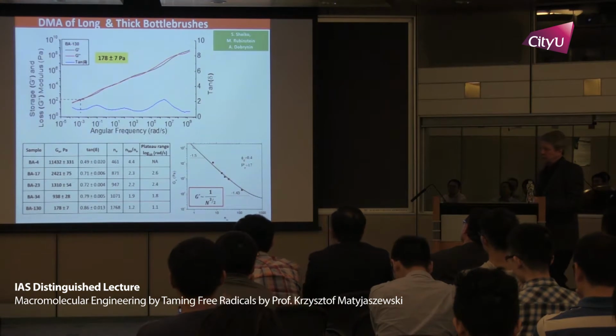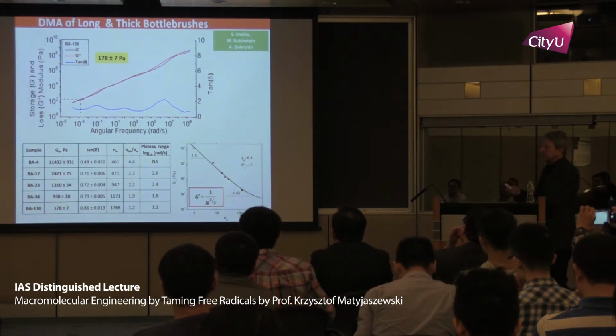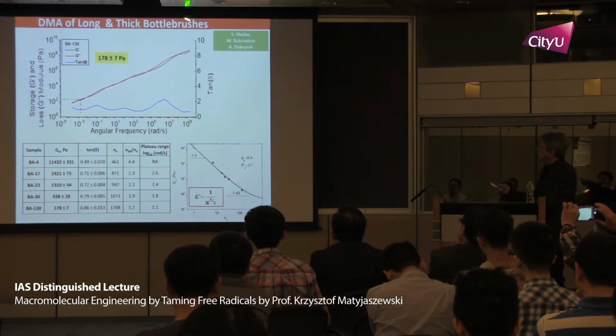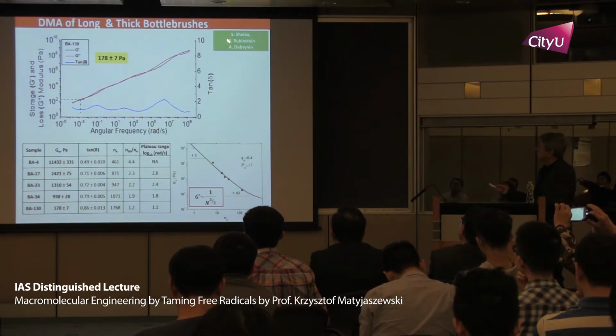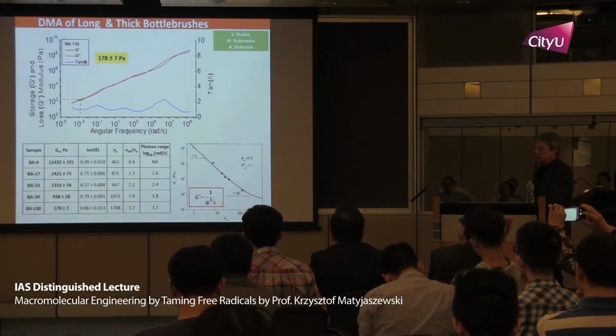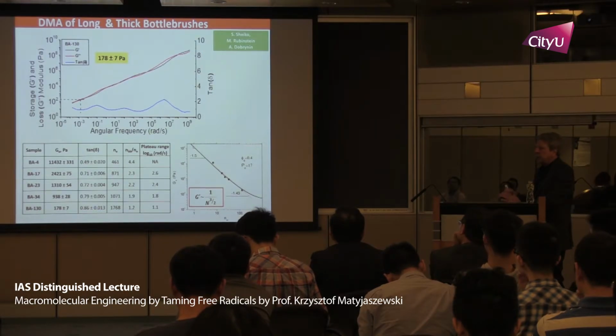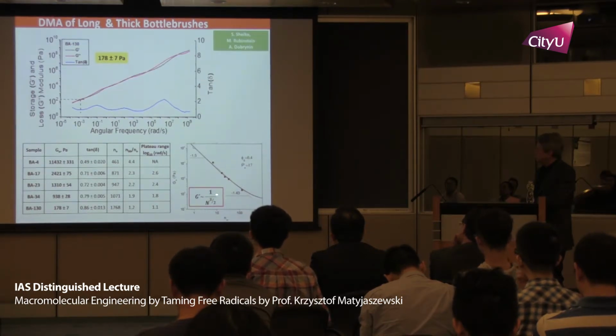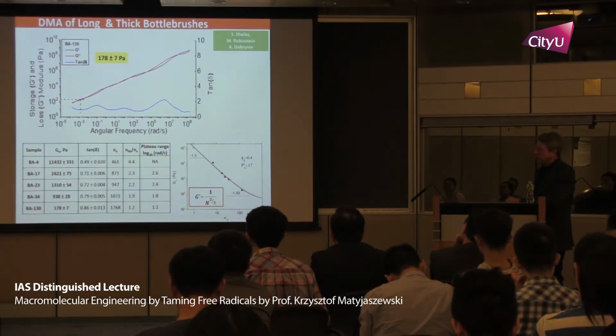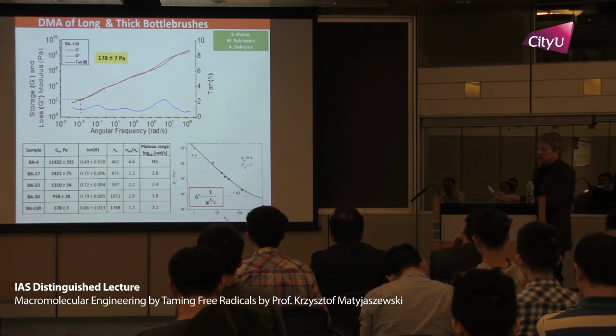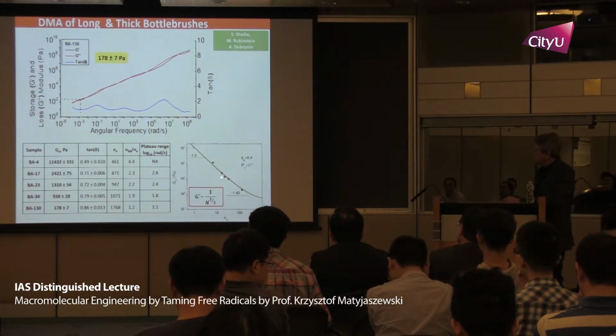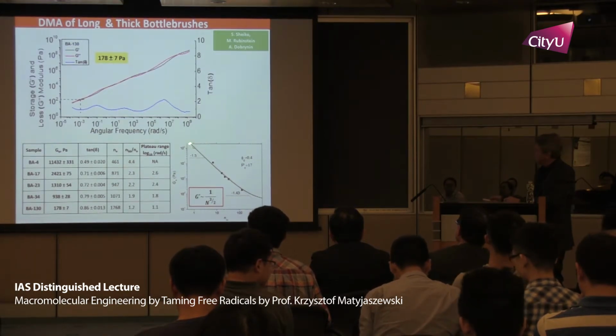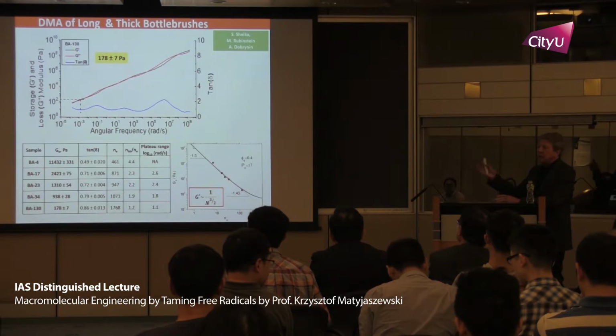What about mechanical properties? We had this project for several years, collaborating with Sergei Sheiko at UNC, but also Michael Rubinstein and Andrei Dobrynin, and they came up with a very simple equation. The terminal modulus should scale with a power of negative 1.5 of the length of the side chain. So this broken line is the prediction, and these are experimental points. This is polybutylacrylate, million molecular weight.